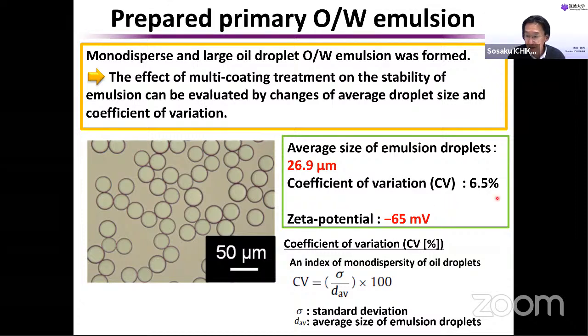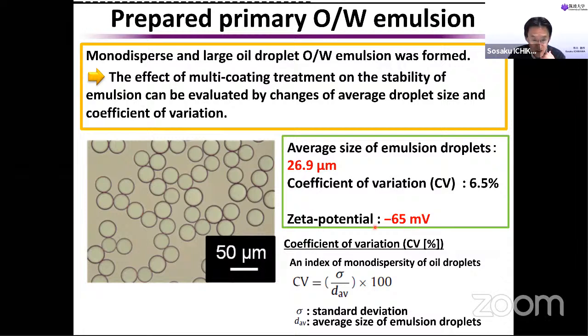But in this case, only 6.5 is very uniform, as you can see, the oil droplets. And the zeta potential, which means the surface charge of the oil droplet, is minus 65. It's a very high negative charge of the oil droplet.